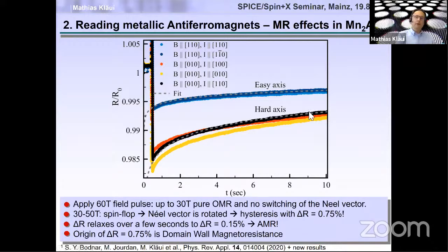And if you go back to the slide where I showed you the domain structure, you could see that after the application of a field, we still had a lot of domain walls. So the interpretation here is that directly after applying the field, we have no more domain walls. We have a fully aligned state. Later, we have the formation of domain walls, so that you have a domain wall magnetoresistance that gives you this 0.75%, and the pure AMR is the 0.15%. This is something that we are still working on. I think it's quite interesting because it allows you to read out the state of metallic antiferromagnets.